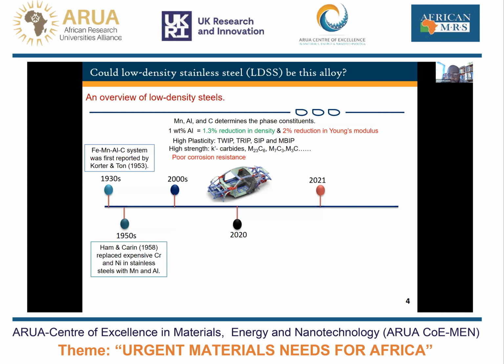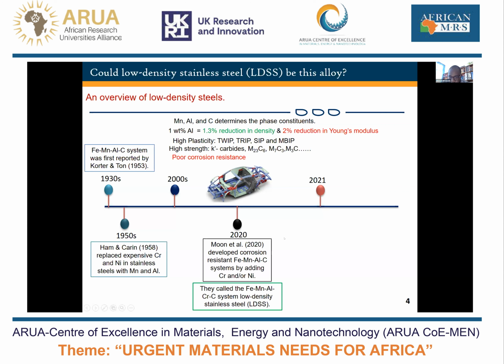But despite the fact that we have good plasticity, high strength, and reduction in density, all the alloys that were developed around then had poor corrosion resistance until 2020, when Moon thought, okay, it would be nice to add a little bit of chromium or nickel or a combination of the two to Fe-Mn-Al-C systems, and he was able to arrive at a set of alloys that has between 3 to 5% of chromium, and that gives improved corrosion resistance than most of the stainless steels that are already in the market.